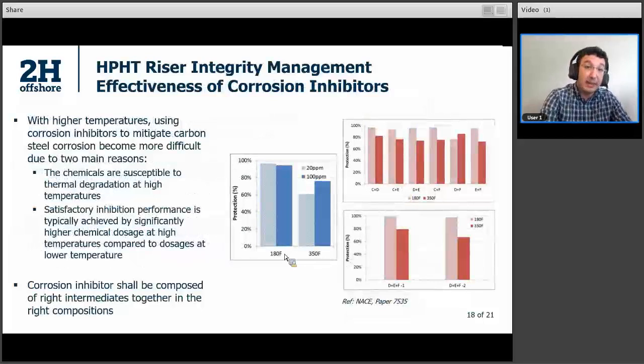Next one is the corrosion inhibitor. Basically, corrosion inhibitors are used to mitigate carbon steel corrosion due to the internal fluid. As you increase your temperature, it becomes more difficult to use corrosion inhibitors. Typically, the effectiveness of corrosion inhibitor reduces as you increase your temperature. There is a nice paper, and this plot here clearly shows it. For the 180 degree F temperature, you have the same corrosion inhibitor in different concentrations, 20 ppm and 100 ppm, and as you see, the corrosion protection is almost 100%. But if we increase the temperature to 350 degrees F, then suddenly the protection goes down. So that's one of the disadvantages.